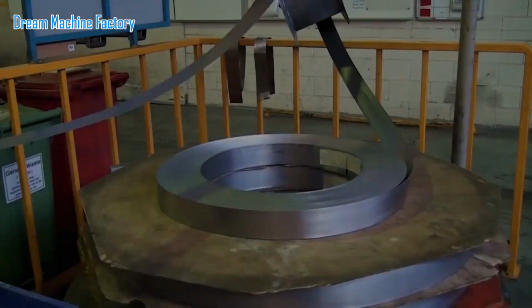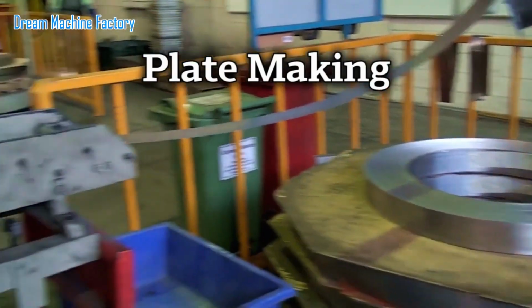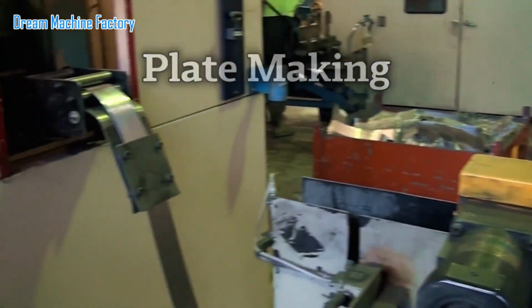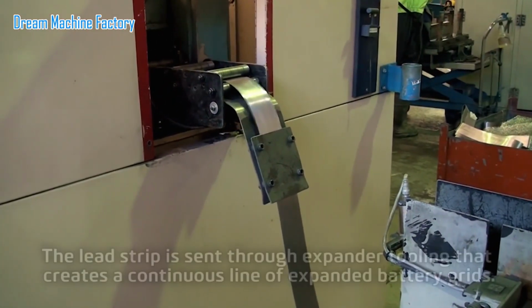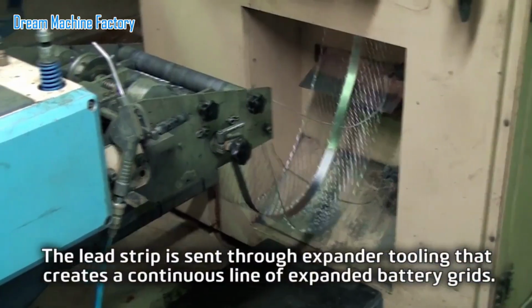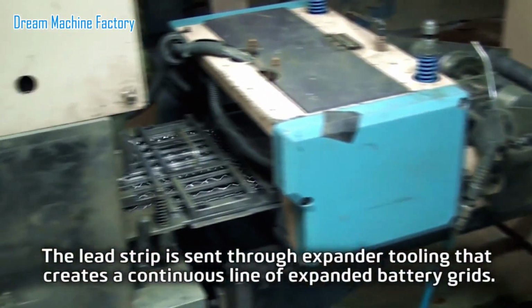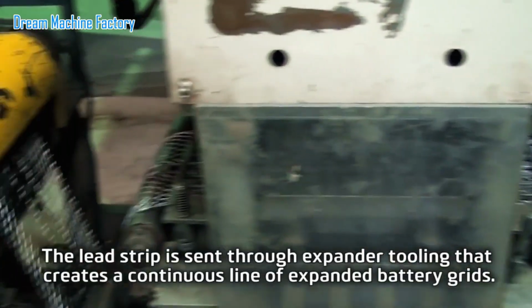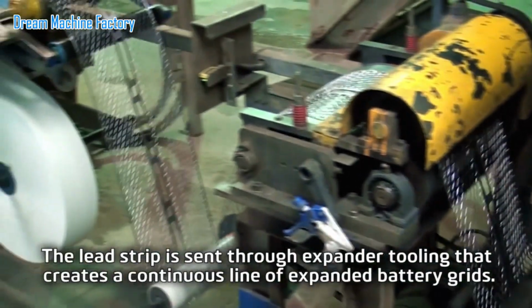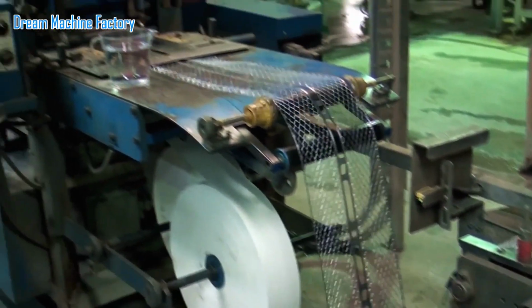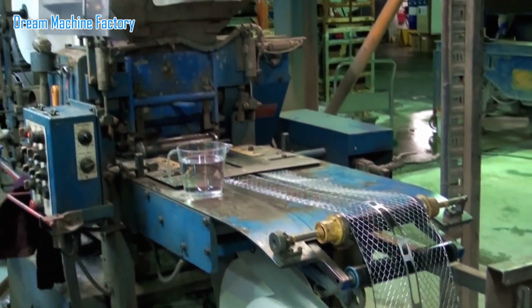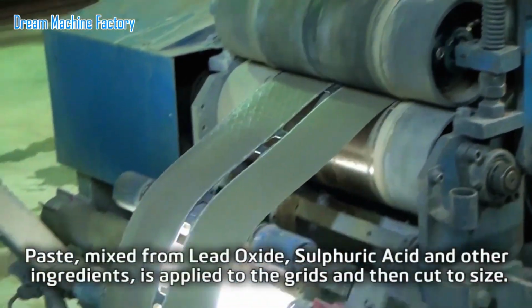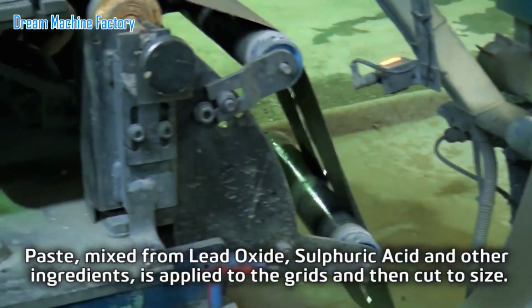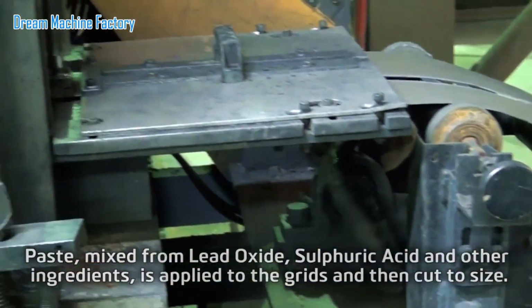In the plate-making stage, the chilled lead strip is fed into expander tooling that stretches and perforates it into a mesh-like structure, forming continuous battery grids. These grids are coated with a specially formulated paste made from lead oxide, sulfuric acid, and additives. After application, the pasted grids are cut to size, stacked, and cured in a controlled humidity and temperature chamber to harden and strengthen the plates.